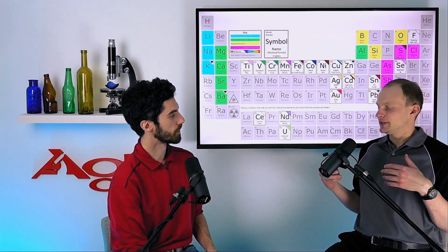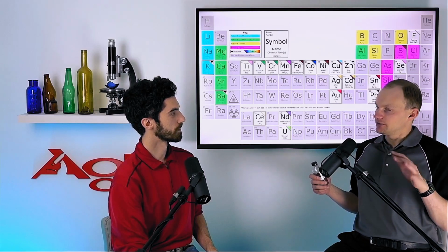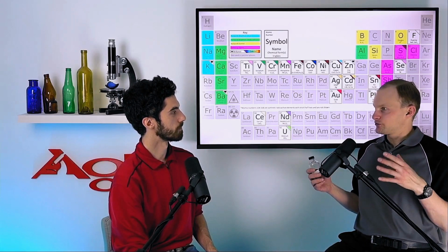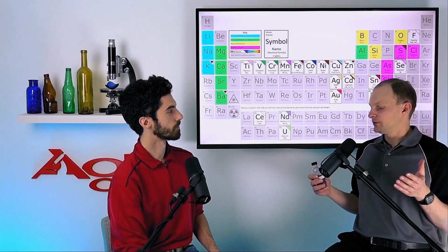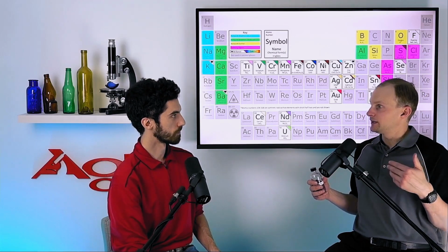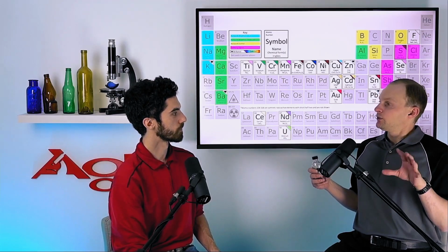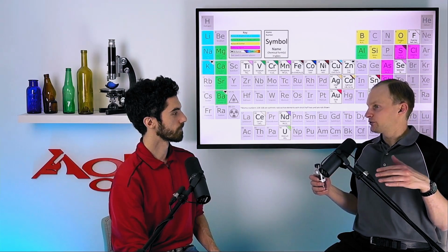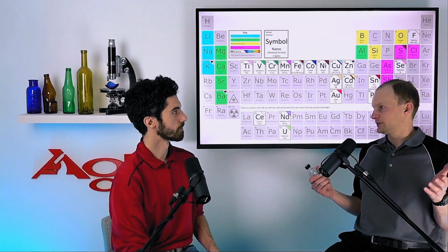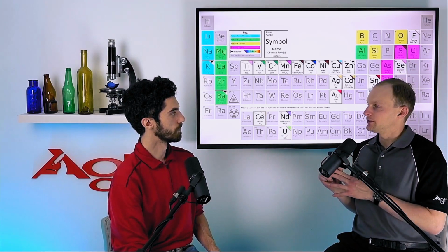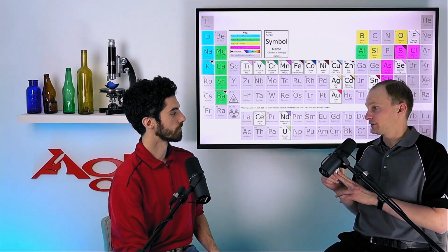So it can have different numbers of electrons that are missing from its outer shells, and that gives it different color properties. Similar to selenium, iron and other elements, we can alter whether the furnace is relatively oxidizing or relatively reducing, and that will give us different color states. Copper typically gives us a nice light blue color when it's in the glass.